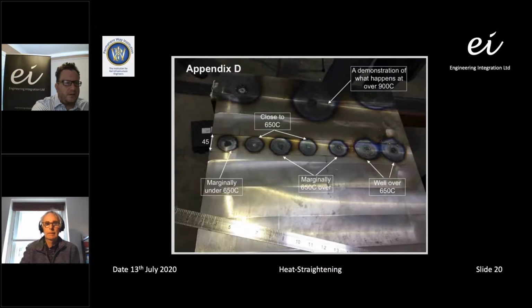You can see there that we've undertaken some heating trials on a test piece. So we're using the heating patterns to define what temperature the steel has been heated to. We take a test panel that is the same thickness and same material grade as the structure, and we apply heats to it. You can see there that we've applied a series of heats, increasing in temperature. We've identified that at 650 degrees, there will be a circular heating pattern of 45 millimeters. And we use wax crayons effectively that melt at different temperatures. You can see there's a blemish within the center of each of the heating patterns. So we put these crayons on, and they have different categories of heat.